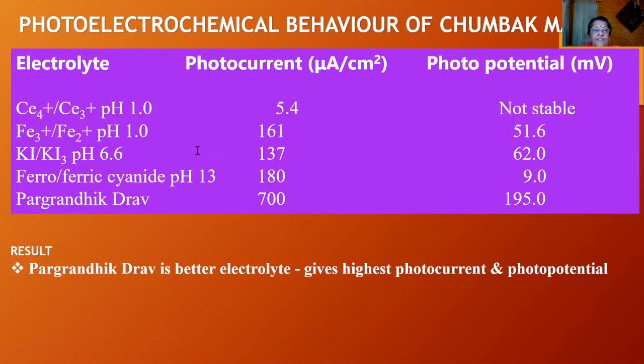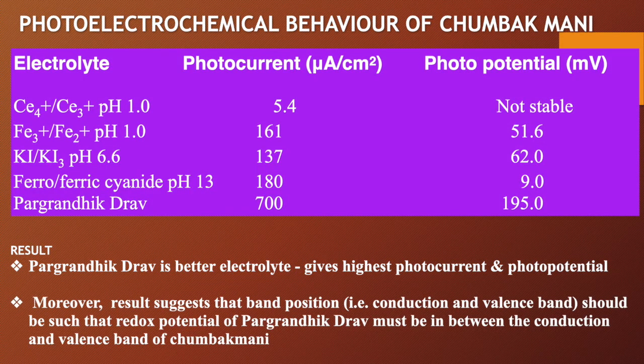And photoelectric property, this was the last thing that we wanted to do and we studied. So you can see in cerium, photocurrent and photopotential, we measured them, and you can see these were the data. But when we used Pargrandhik Drav as the electrolyte, we got the highest photocurrent and photopotential. So both were highest. So this electrolyte is much better than those that we know.